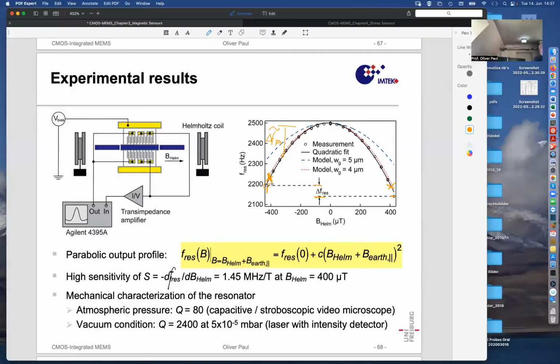So if you rotate your Helmholtz coil in the lab and you make a measurement, you will see that the delta F goes up, and then it goes to 0 again, and it goes to negative, and it goes to 0 again as you complete the full circle. So you have to make a compass. It's a big compass. A Helmholtz coil plus a microsensor. So at least, this was proof that you can measure the Earth's magnetic field. A compass, which is hard with a semiconductor sensor based on silicon.